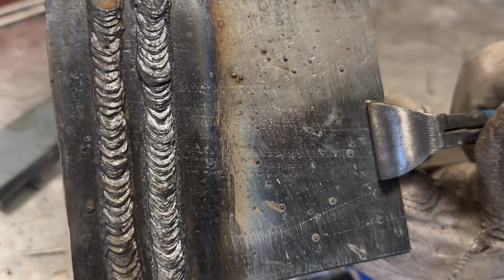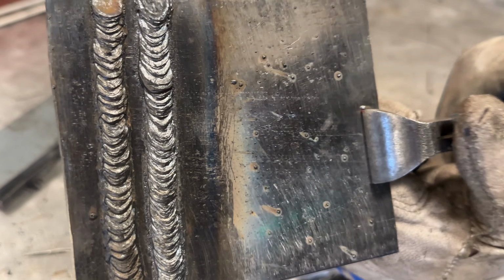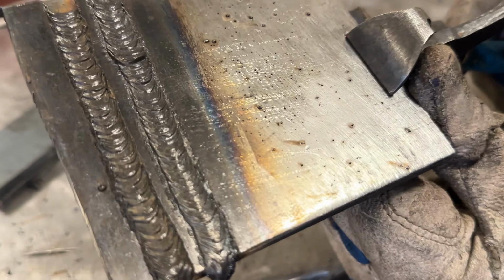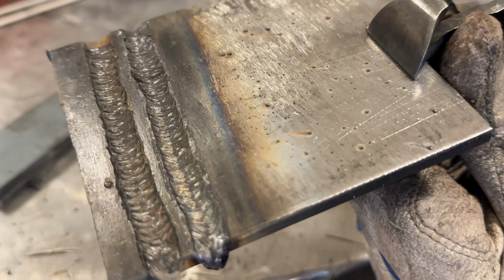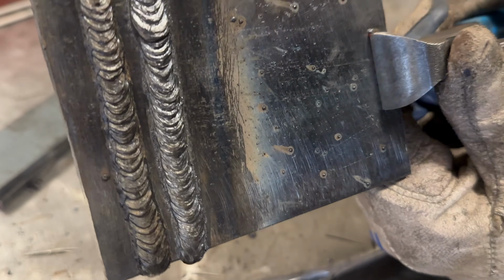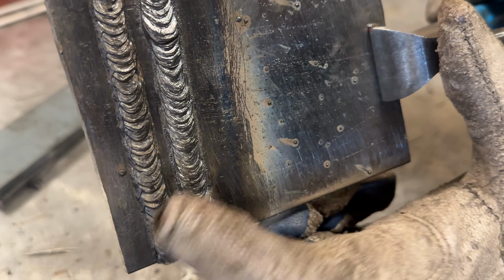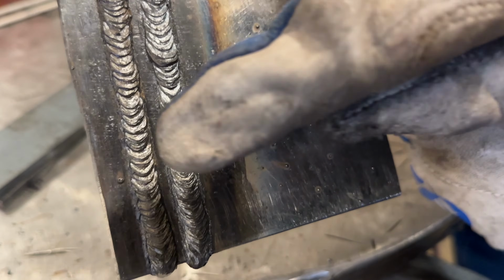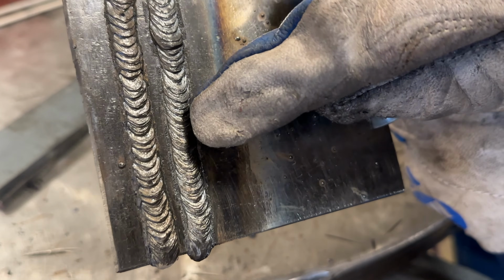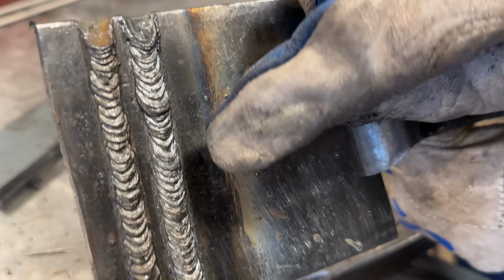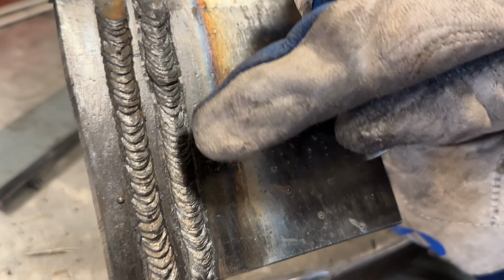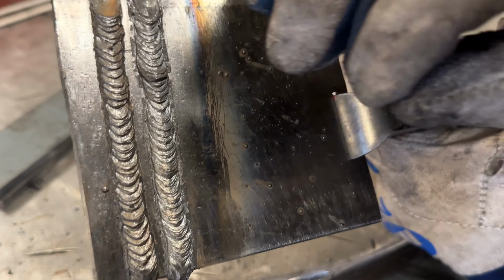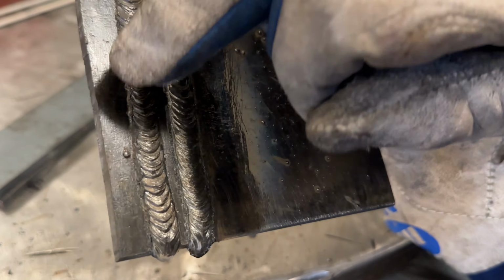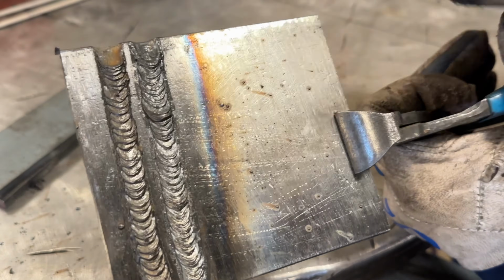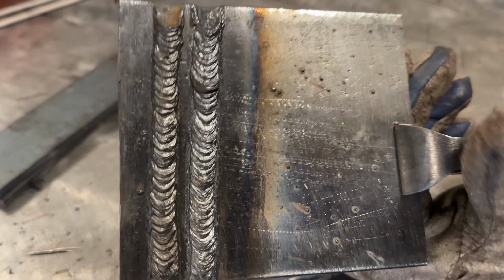Now, if you look there, you see it has ripples. You can see my little bit of a rough restart. But the ripples are overall more, I guess, smoother, like they're less defined. Same amperage, but you compare 5P Plus versus 5P. A little bit more liquidy of a weld pool, a little bit slower of a freezing rod. Tends to wet out and makes better overall looking welds, I find. I mean, 6010 5P red rods are real rough running bastards, but not too bad.